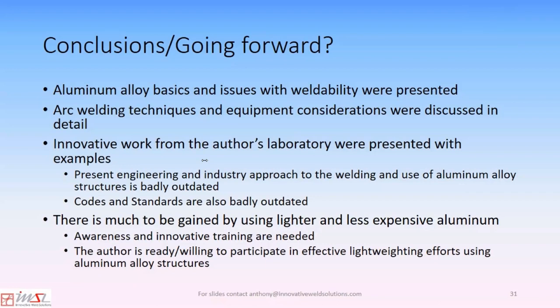Answered, yeah. Can we use normal spot weld machine for aluminum welding sheet? Yes, you can use normal spot weld machine for aluminum sheet thickness of 1 millimeter if the welding currents that the machine can deliver are at least about 40 to 50,000 amperes. As you know, aluminum spot welding requires higher current, shorter weld times, and higher weld forces. So you're looking for at least about 700-800 kilogram force capability, and you are looking for about a 40 to 50,000 ampere current capability, and you are looking for fast follow through.